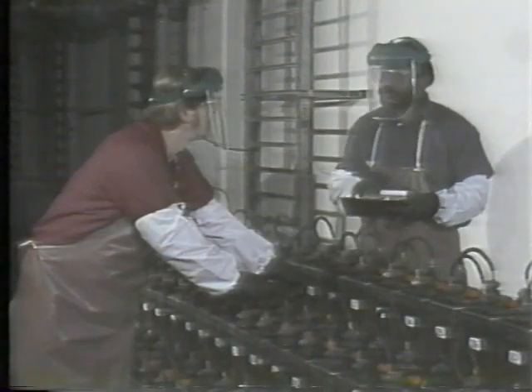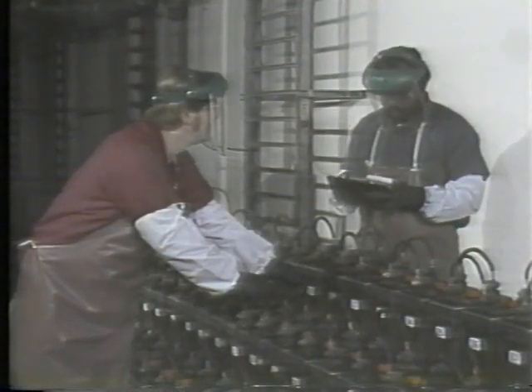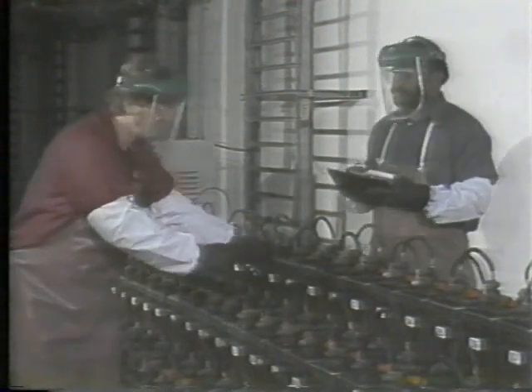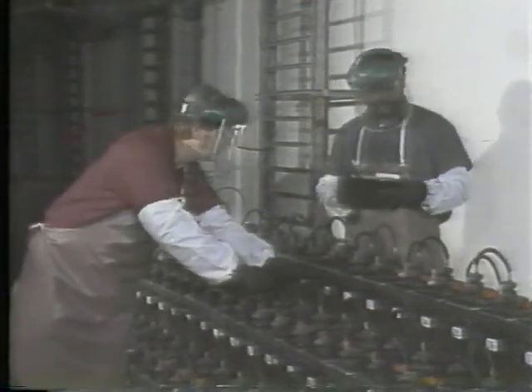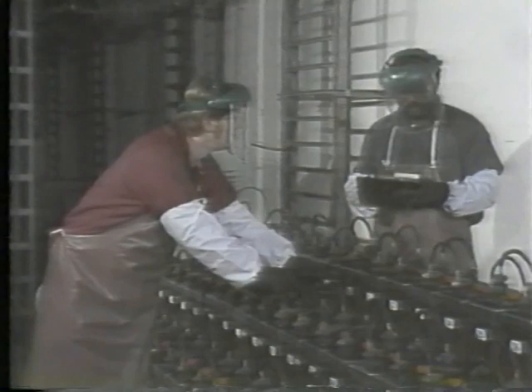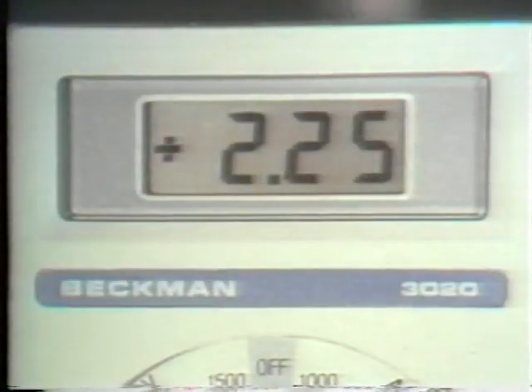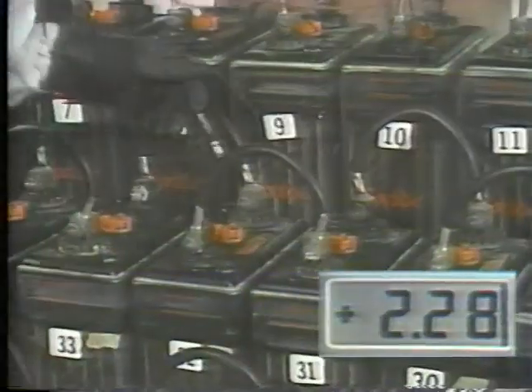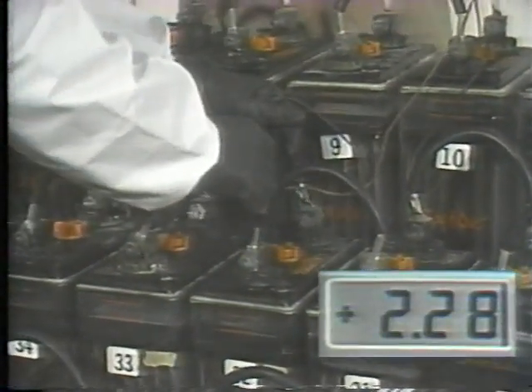There's definitely a problem with the cell, but before taking any further corrective action, the two workers will continue with the routine test procedure by making a cell voltage check. Each cell is tested individually with a voltmeter while the charger is on and under normal station load conditions. Most of the cells show the expected reading. Up to this point, they're all close to 2.25 volts.